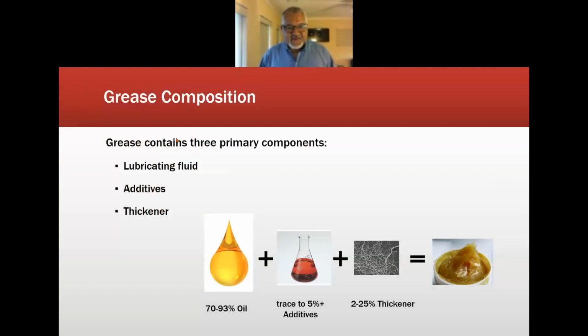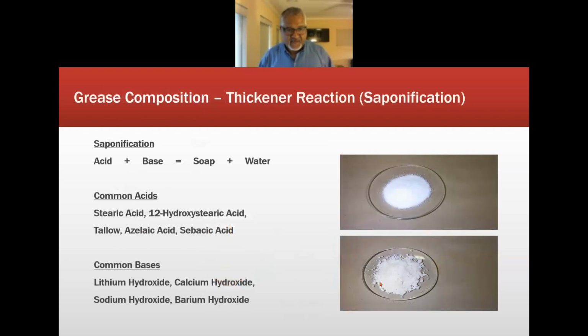So grease contains three primary components: the lubricating fluid, the base oil, the additives, and the thickener. These numbers may vary, so 70 to 90% base oil, just a trace of additives, 5%, just like in many lubricants, just a little bit of additives, and then thickeners 2 to 25%, just depends on what NLGI grade you want to meet. Well, how do you make a grease?